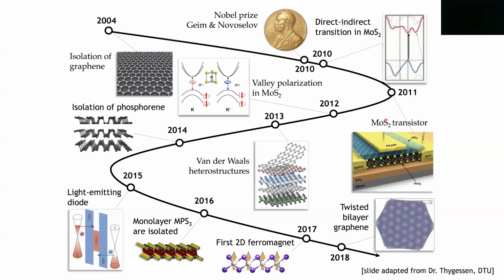One year later, the first transistor using a 2D material was created, in this case with molybdenum disulfide. More research on molybdenum disulfide followed, taking into account the different values of polarization. Then the dream of Richard Feynman to combine different materials to create van der Waals heterostructures became possible in 2013, but there's no magnetism at all at this point, except with atoms added to magnetize graphene. Other elements of the periodic table entered the game to make single layers, for example phosphorus, like phosphorene. And finally, in 2016, it was possible to isolate one single layer retaining long-range antiferromagnetic behavior, in this case for FePS3.